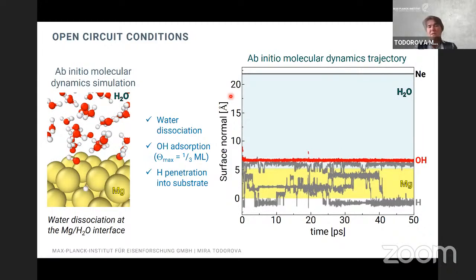And if we now plot the trajectories as they evolve over time, we can see what is going on. We have blended out here all the magnesium trajectories that correspond just to the atoms moving, as well as the trajectories of water molecules that are not directly participating in any kind of reactions at the surface, and only leave here explicitly trajectories for water molecules that are involved in what is happening at the surface. We see this water dissociation and the formation of OH and hydrogen. And the hydrogen stays within the magnesium slab, and the OH remains at the surface.